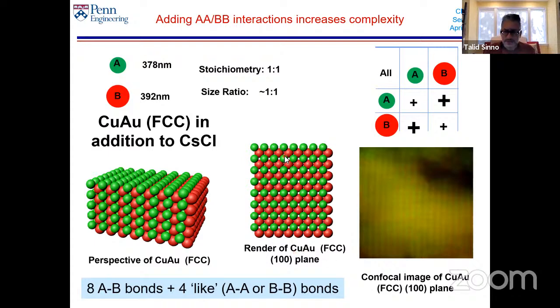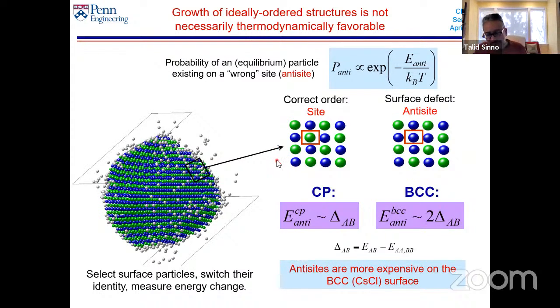So now we can take a little sidestep. I don't want to spend too much time on this, but I just want to point out that when these crystallites are growing, this is just a picture from a simulation, particles that are landing at the surface can land in the right place, or they can land in the wrong place, in which case they form a defect. And the defects here that we're talking about would be having an A particle land in a site that's meant for a B atom, or a B particle landing on a site that's meant for an A atom. And these are known as antisite defects.